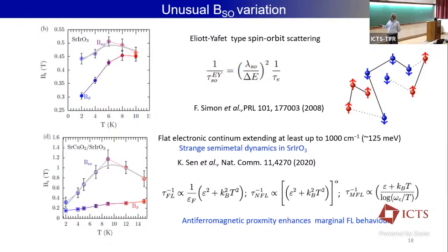Once we know that this is strange semi-metal dynamics, and we know how the scattering rate changes when you go from a Fermi liquid, where it has T-square dependence, to a non-Fermi liquid, where the quasi-particles have some long-range interaction, and if the interaction is not strong enough, it will show a logarithmic behavior. This is what the scattering rate looks like for the marginal Fermi liquid or strange semi-metal. When I put this in as the momentum relaxation time, we are able to account for the unusual variation of BSO with temperature.